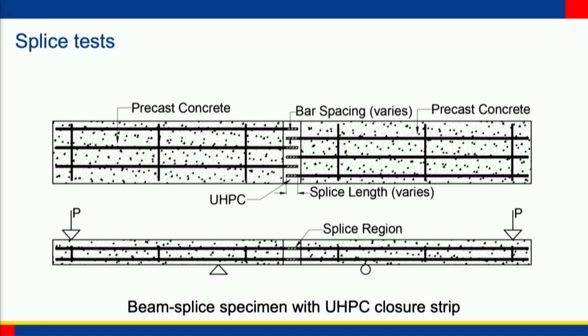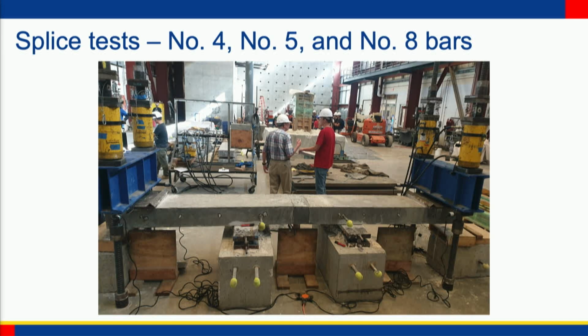So we get a variation in cover as well. We tested number 4, 5, and 8 bars. That's 1/2-inch, 5/8, and 1-inch diameter bars. That's the test specimen. You can see the precast sections at either end. This is in our lab, and in the middle is the UHPC closure strip.